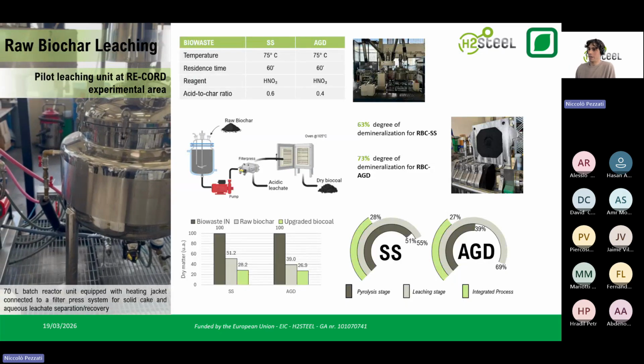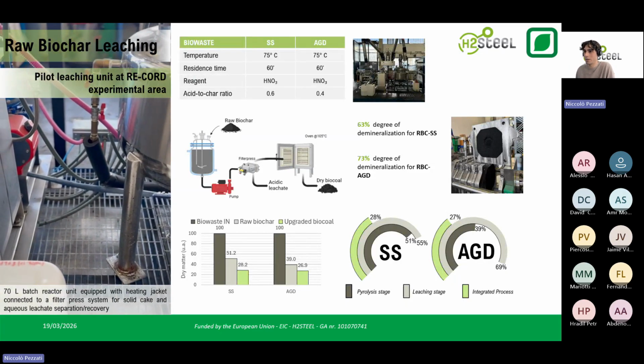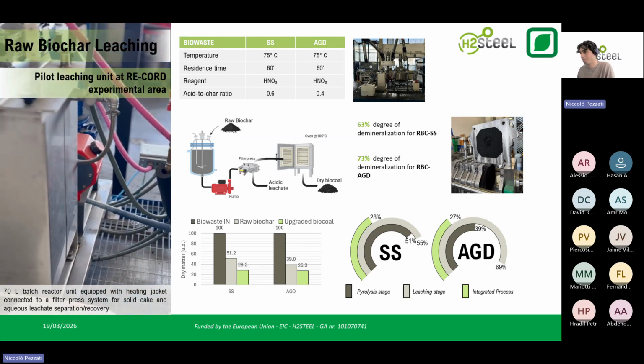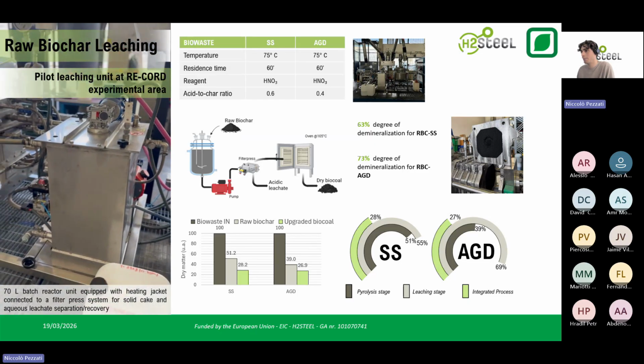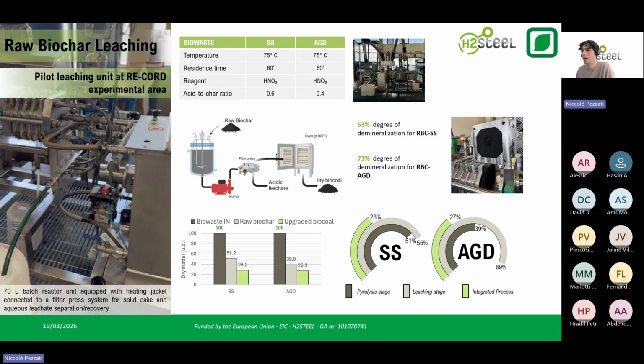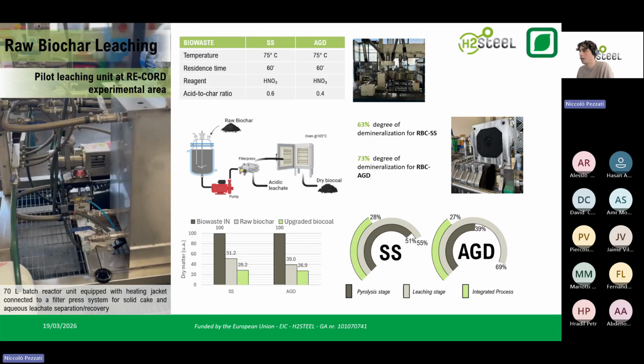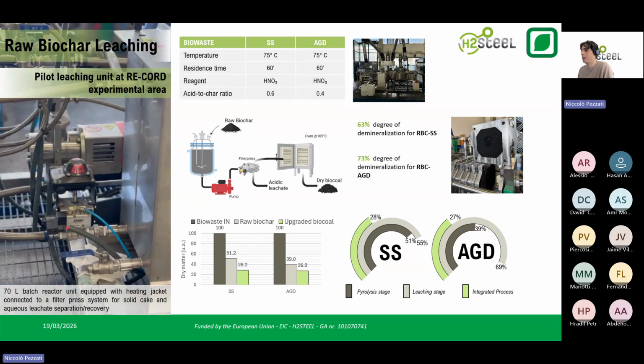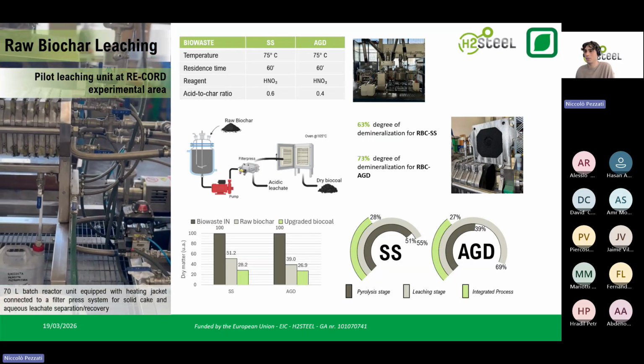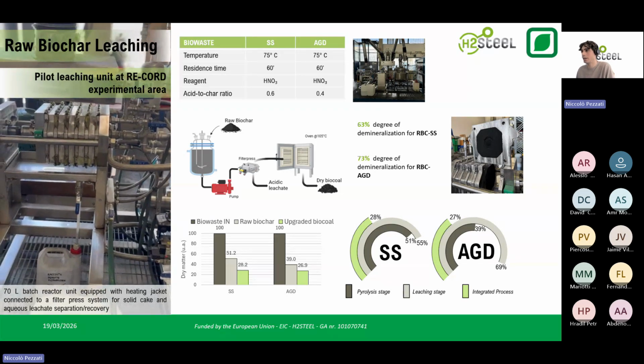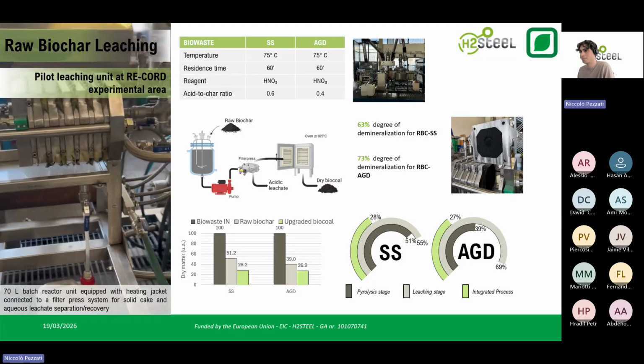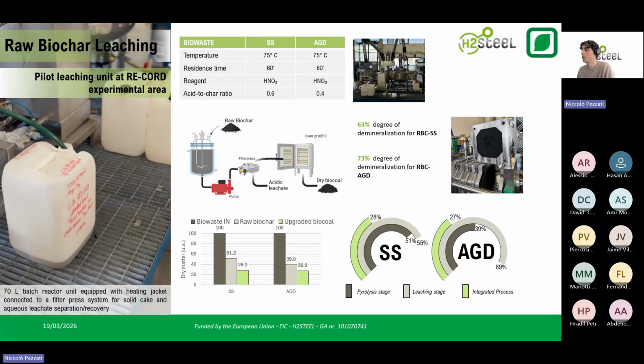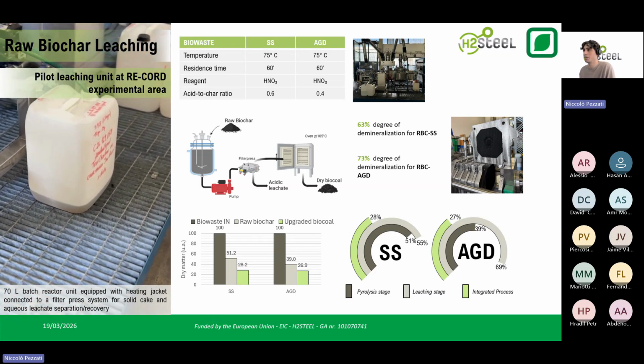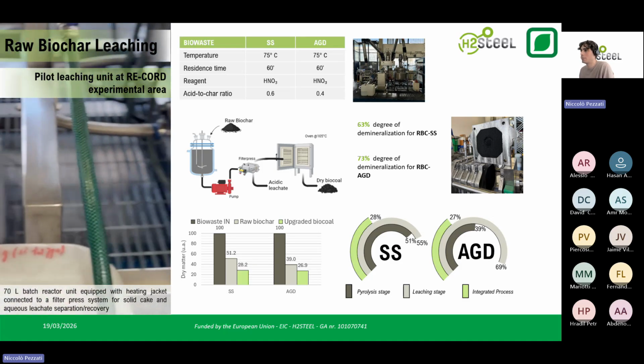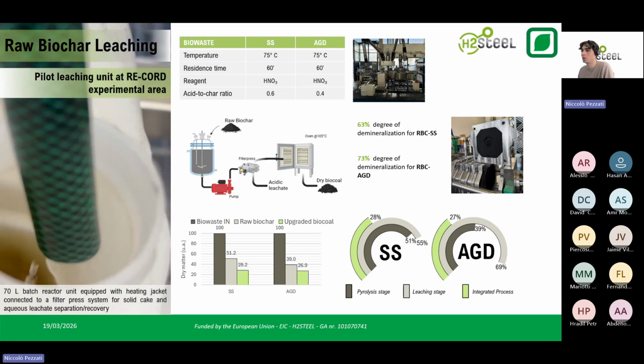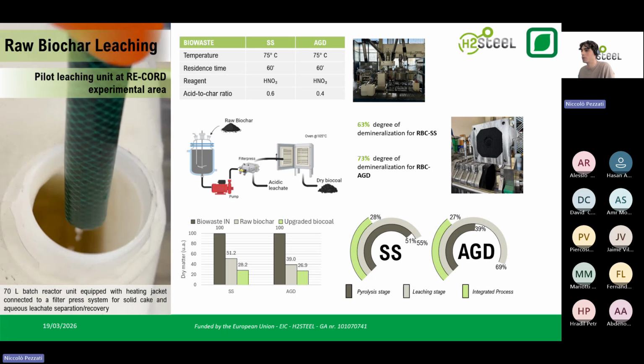So to overcome, as I was saying, the shortcomings of having high ash content in the raw biochar, we create this solution in which we are able to remove the ashes from the solid with the aid of an acidic treatment. The acid reagent that we used is nitric acid. So the treatment, which has been performed on a pilot scale, as you can see here in the clip, is performed at a temperature between 70 and 80 degrees Celsius with a dwell time of 60 minutes and an acid to char ratio which can range between 0.4 and 0.6.